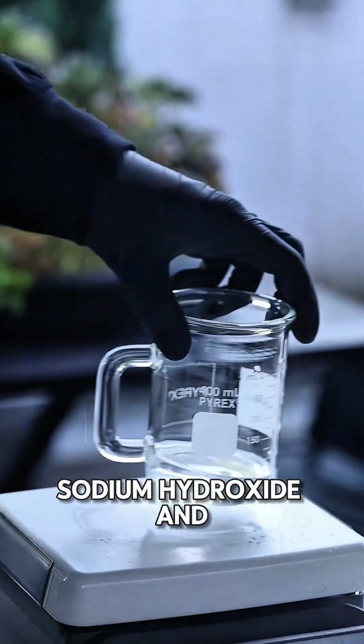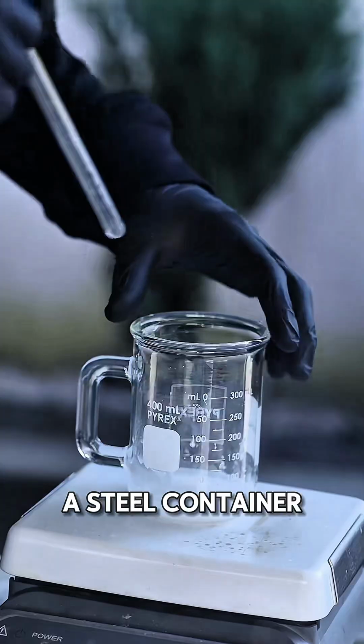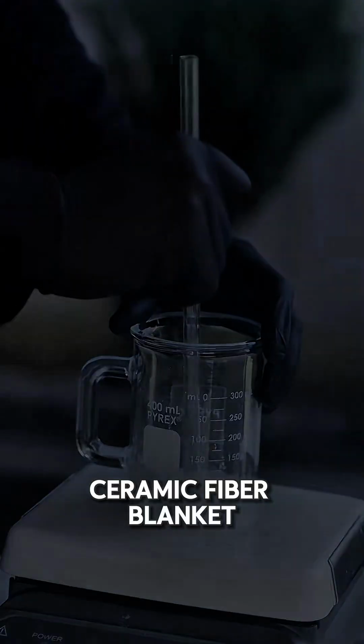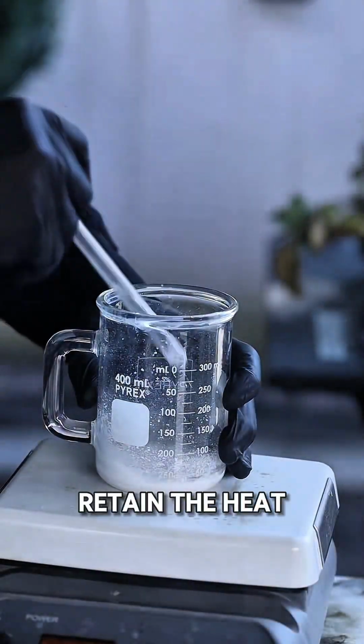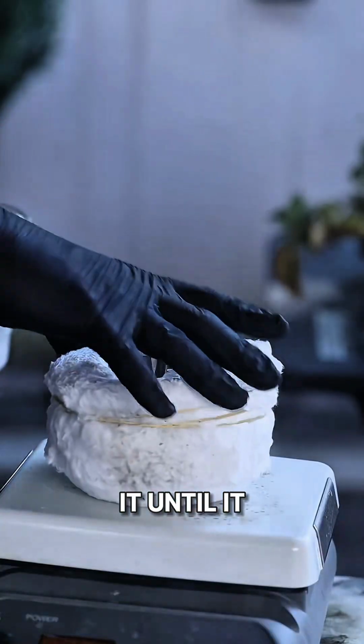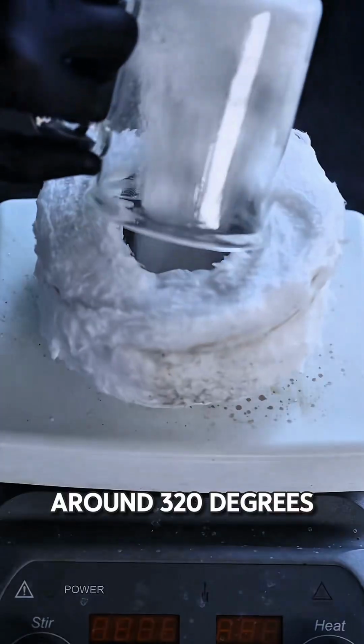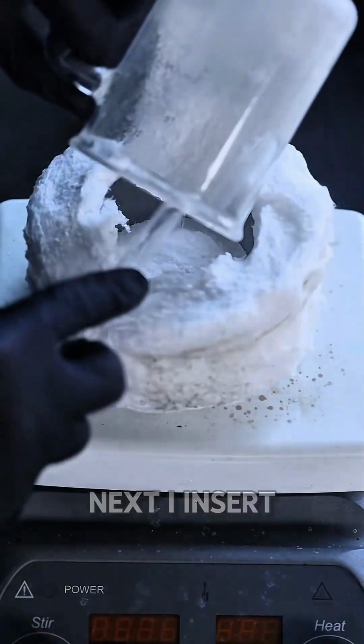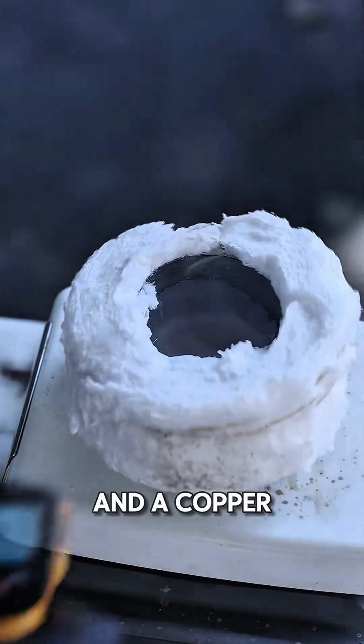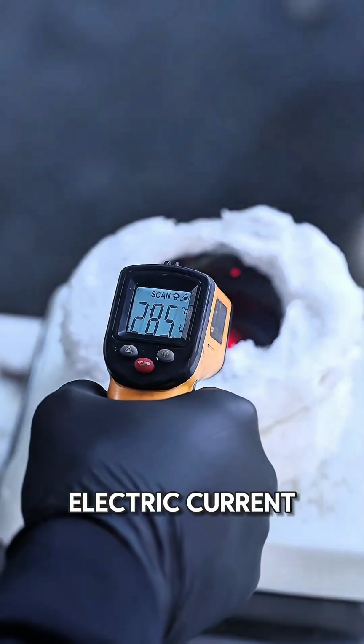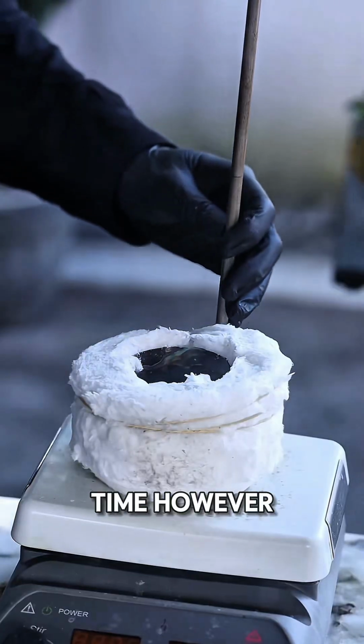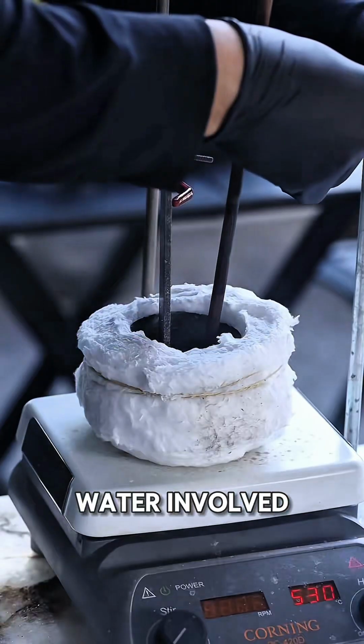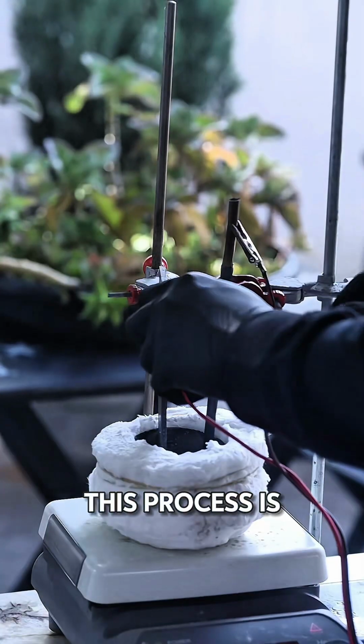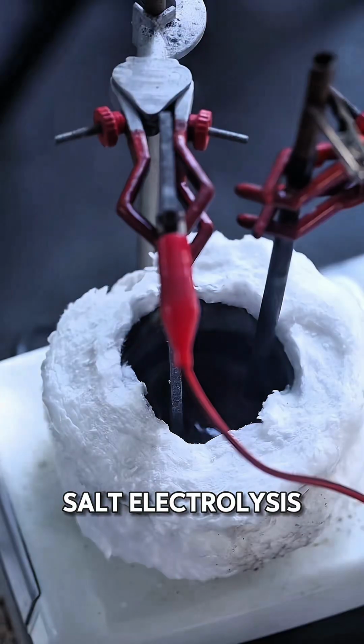I grind the sodium hydroxide and transfer it into a steel container surrounded by a ceramic fiber blanket, which simply helps retain the heat. I then heat it until it melts, which happens at around 320 degrees Celsius. Next, I insert a graphite electrode and a copper electrode before applying an electric current once again. This time, however, there is no water involved. We're dealing with a molten salt. This process is known as molten salt electrolysis.